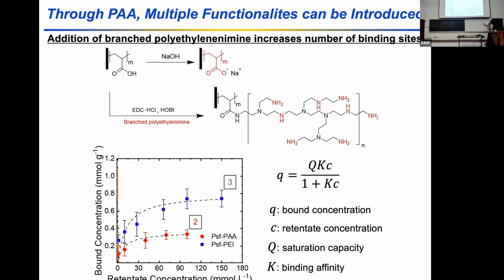The first thing we do is couple branched polyethylenimine molecules to the surface. This creates a higher density of binding sites, so we have a higher ability to remove copper ions from solution. And that manifests in an upward shift of the isotherm for the blue squares, relative to the red diamonds.